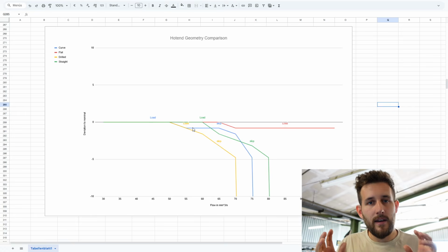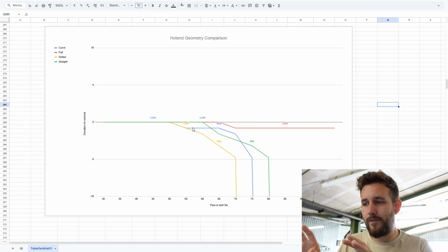because this means basically that it is totally appropriate to SLM print your hot ends, your internal geometries. And while for certain kinds of extrusion and molding, etc., the surface roughness of that process is just not working, for our filament-based extrusion, this is even an advantage. I mean, even if we take these measurements all with a very big grain of salt, it just shows that it's at least equal to that and maybe even on top. What that means is we have total design freeness in all of our geometries that are inside the hot end, and that is a very good thing.